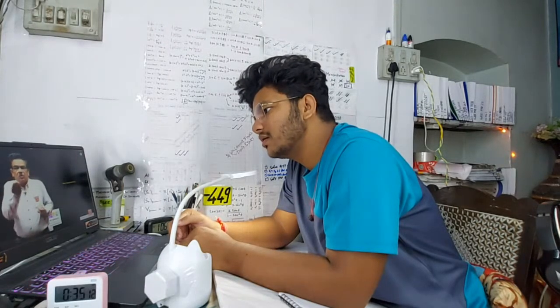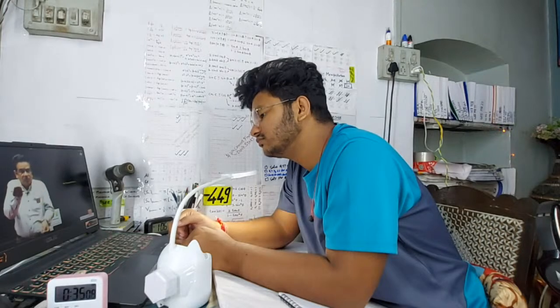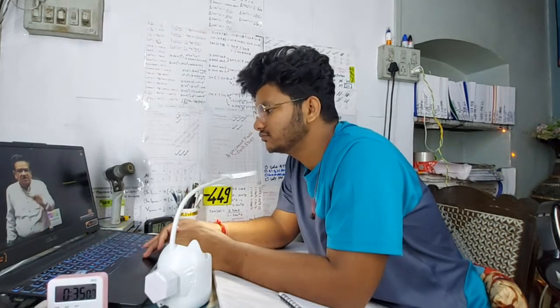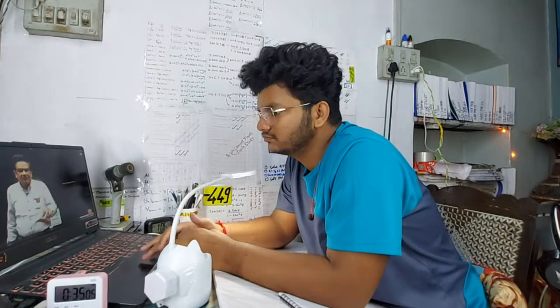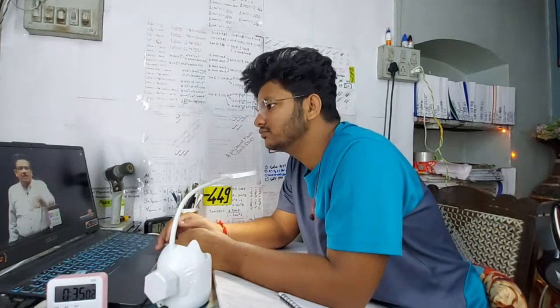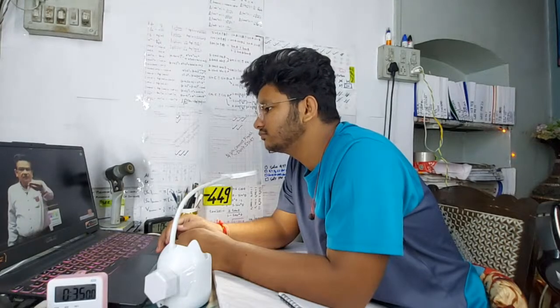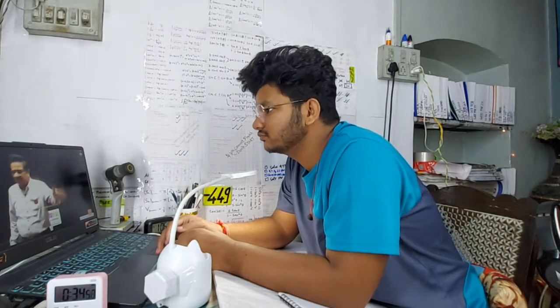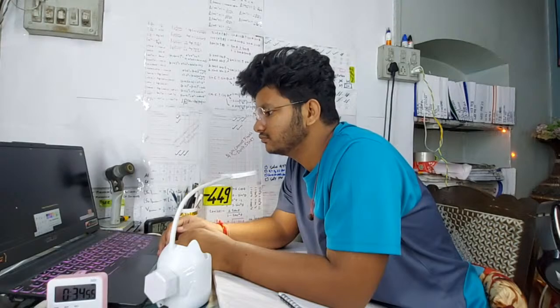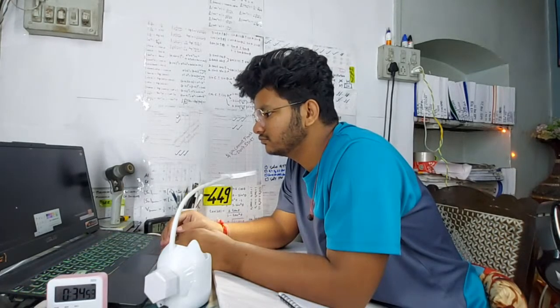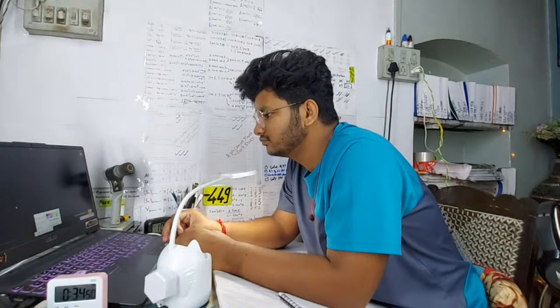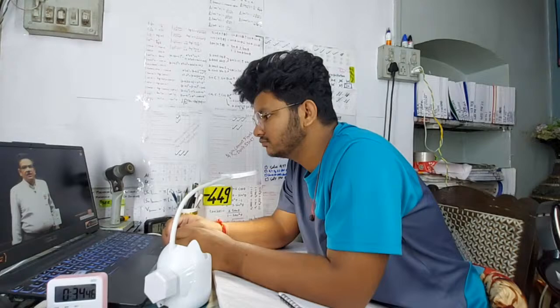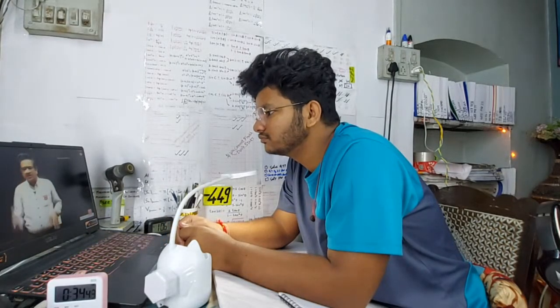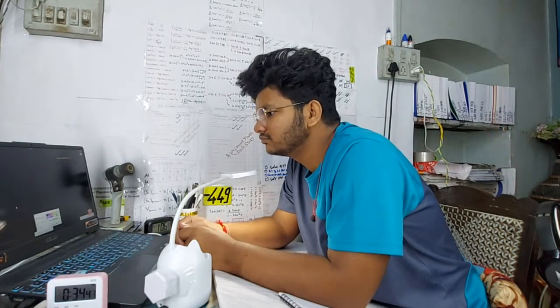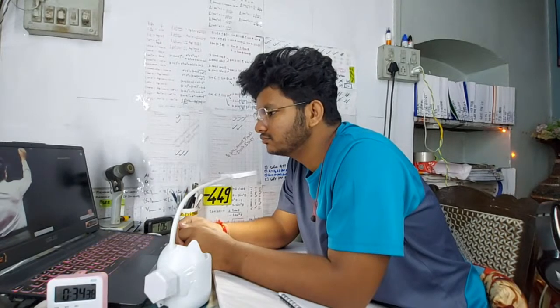If the martensite finish temperature is above room temperature, and you are cooling the specimen up to room temperature, the structure will consist of only martensite. Martensite formation will be only at low temperatures because the martensite start temperature is 210. That means martensite formation will be from 210 and below 210 degrees centigrade only, not at higher temperatures. All right, Girish? So, that is the information to you, Mr. Girish. With that information, I am proceeding to the topic on composites.